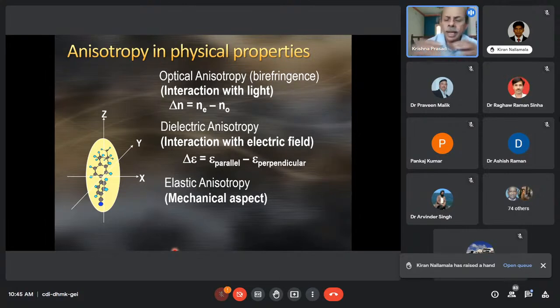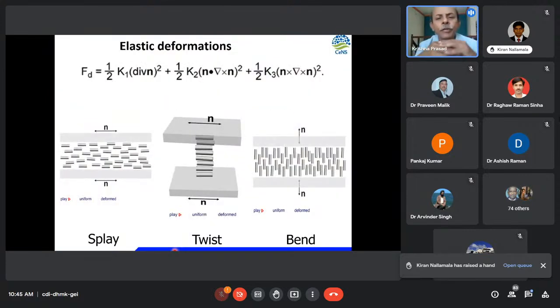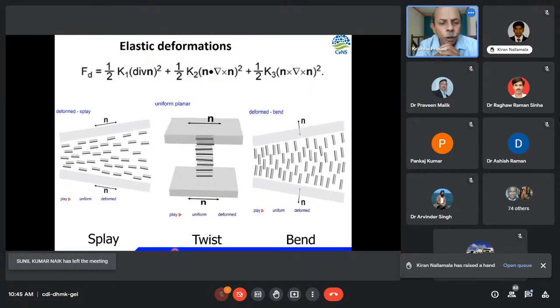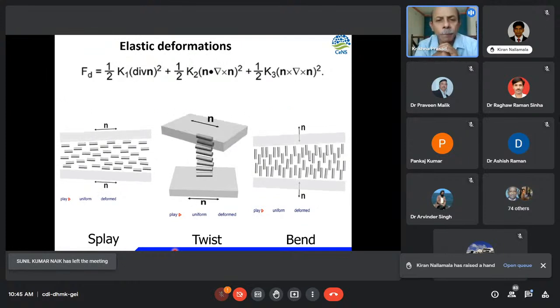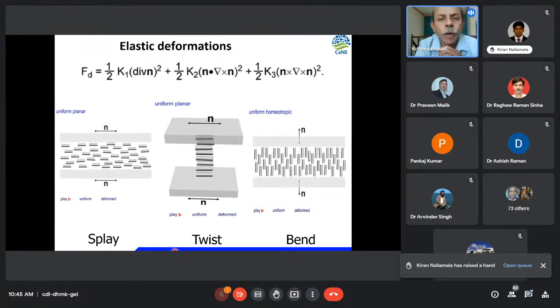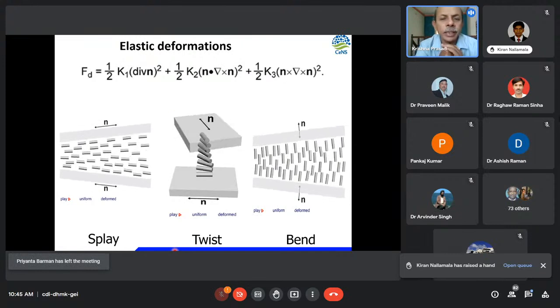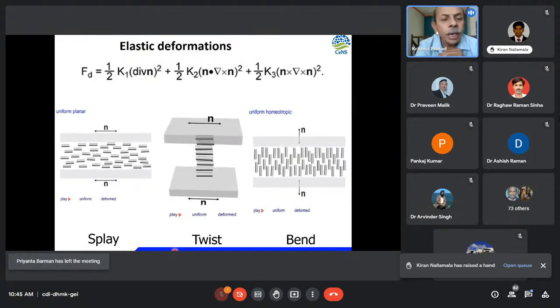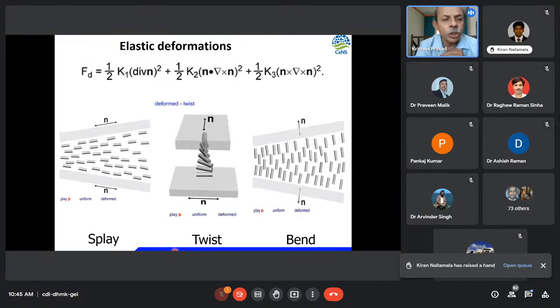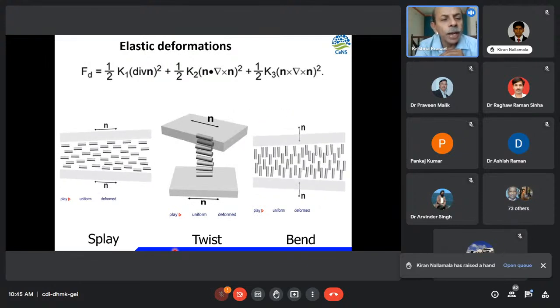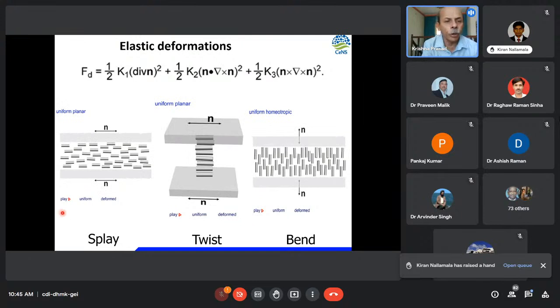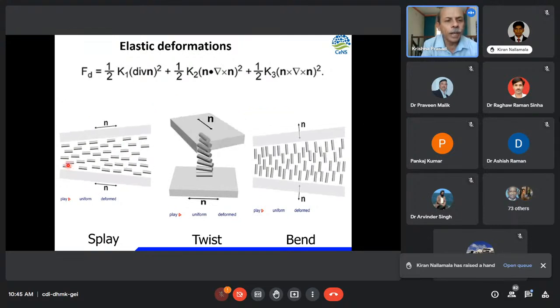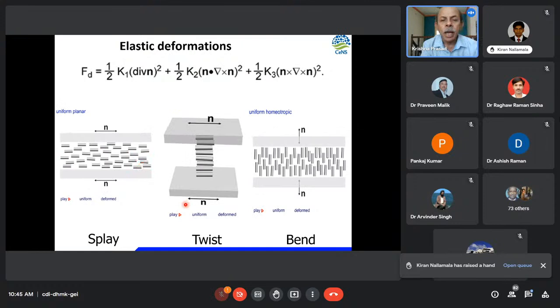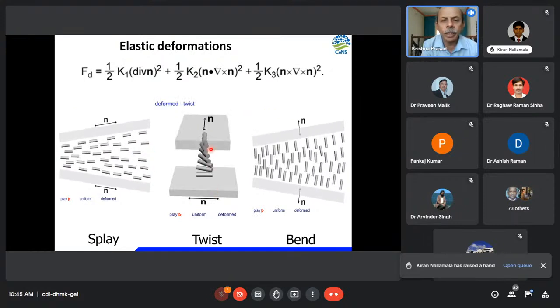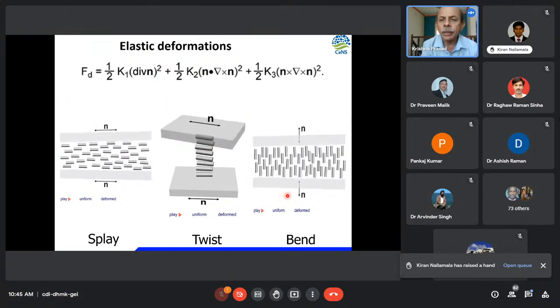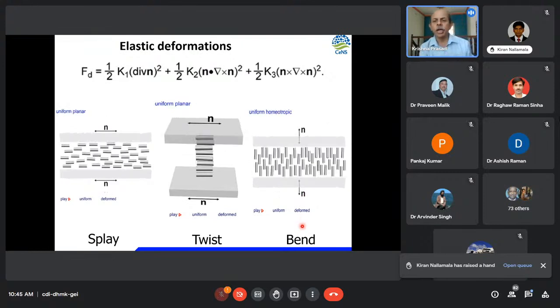And there could also be elastic anisotropy, at least of 3 primary different types, referred to as the splay, the twist, and the bend, depending on how you confine these systems between the containing surfaces. So you can define, for example, if one surface is stretched compared to the other one, then you will have a splay, opening up of the orientation direction of the molecule, splaying from one direction to the other, and twisting from one plate to another. There can be a twisting of the director and the bending of the director, which is obvious from the name given to itself.